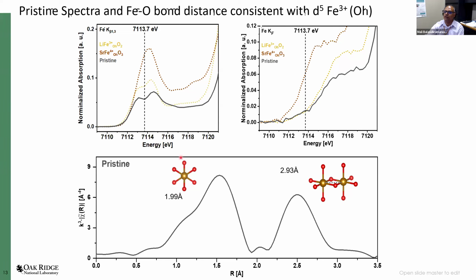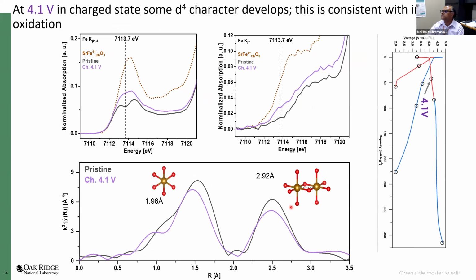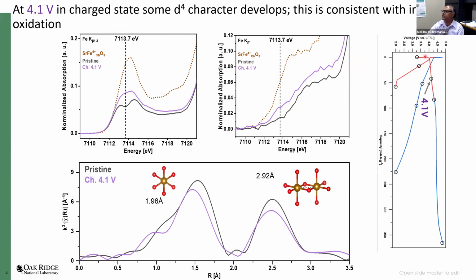We have also performed X-ray absorption simultaneously, and the bond distances that we get are all consistent with what should be expected for a d5 iron 3+ ion. Now, when you charge it to 4.1 volts, where we expect a little bit of oxidation, we do see an increase in this peak, and more importantly, an increase in intensity showing up over here. We believe that this, as we have discussed based on the fingerprinting method, is the signature for the formation of what one can call formally iron 4+, and correspondingly, the iron-oxygen bond distance shrinks a little bit, which is also consistent with the formation of iron 4+ and oxidation of iron.